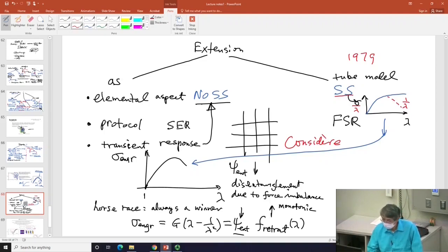Considère studied this for metals. He found that if you have a maximum, your drawing will not be stable. In other words, necking, non-uniform, inhomogeneous. And therefore, people start to say, oh, if you have a maximum, by this time you should neck, or some point beyond the maximum, you should neck. Why not? So convenient.